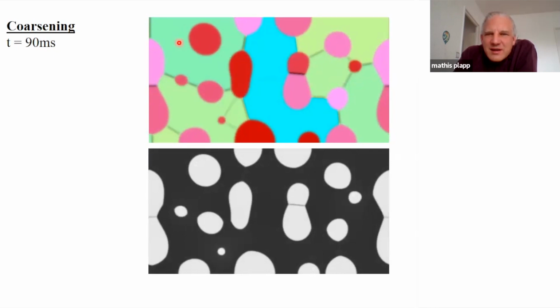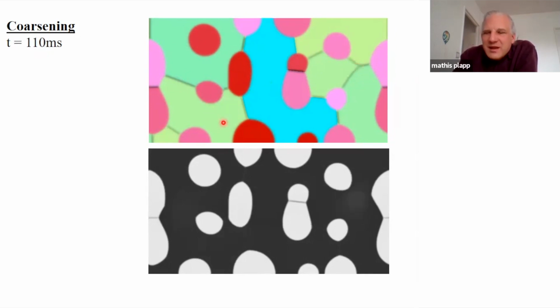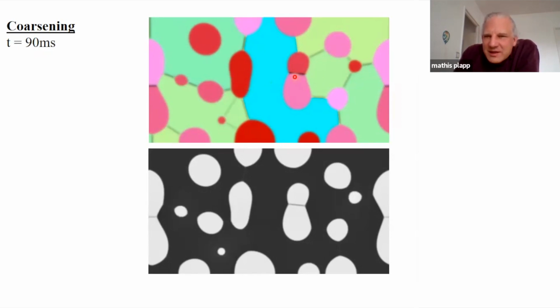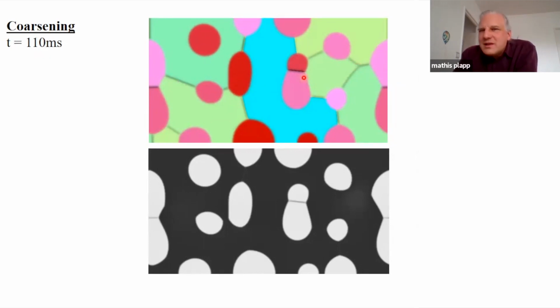So I like the difference between these two pictures because you can see that there are several coarsening mechanisms at play. First of all, there's usual Ostwald ripening, meaning the small domains here of germanium will evaporate and the atoms will diffuse on the bigger ones. For example, this one here will disappear. But there's also another mechanism here. You have two grains separated by a grain boundary. You can see that the grain boundary is mobile, and so the smaller grains will be eliminated by the migration of a grain. So we capture a lot of different coarsening mechanisms in this complex material.